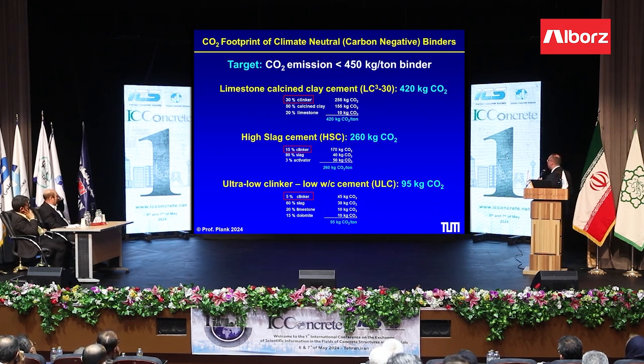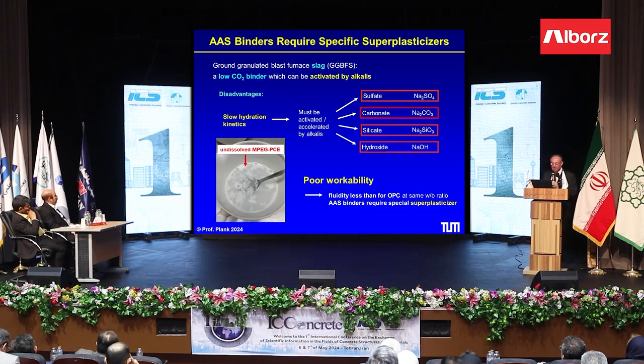Some other examples, and this is really what we work a lot on in Europe, these climate neutral, carbon negative binders, like this with calcined clay here. Please make a notice here, it's LC330, which means it has only 30% clinker, the common LC3 has 50% clinker and therefore is not climate neutral. Or a high slag content with 80% slag, or this ultra low clinker cement with 5% clinker, which is something they use in India. And so you see it is possible to formulate very climate friendly binders.